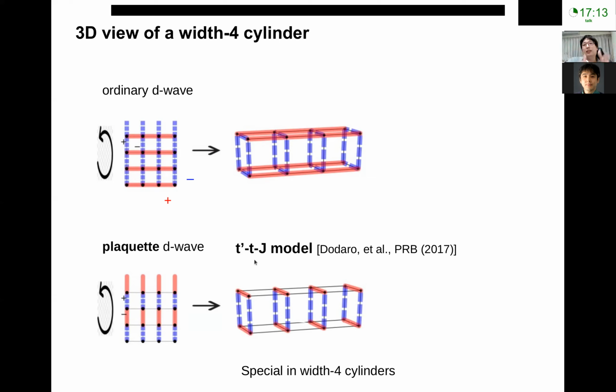So the D-wave means you have different sign on the vertical and horizontal directions. If you just look at one single plaquette, it's also like different sign between the vertical and horizontal bond. You can think of it as the D-wave only happening on each plaquette, and the system becomes kind of effectively a 1D system. We think this is the reason why you would then have this quasi long range superconductivity.